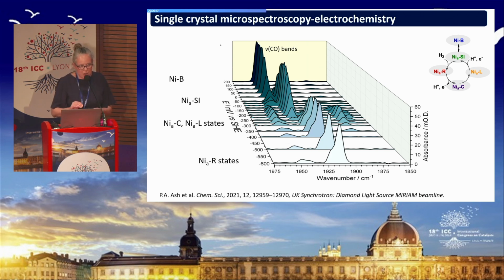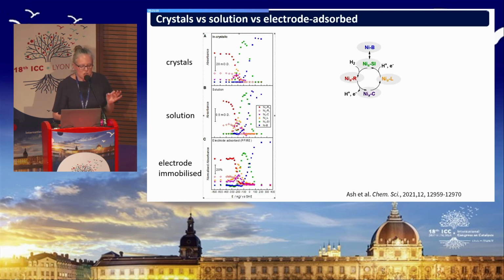So what I'm going to show you now is a series of as yet unpublished structures for hydrogenase in a whole range of redox states, where we've used this route map as our way of dialing up the state we need to get to structures of all the different states of the hydrogenase active site. And just to follow on the route map idea, what we've done here is to plot out the intensities of the bands, giving us a measure of the absorbance, giving us a measure of the concentration of each species that we have at each potential. So this is potential along the x-axis here, and the concentration of different species shown in colours that map onto the colours of this catalytic cycle image over here.